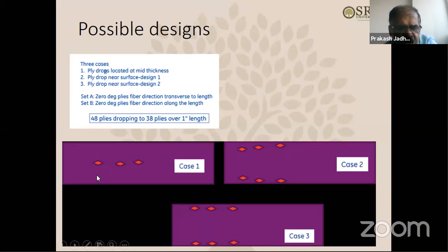So first we tried the coupons with ply drops located at the mid thickness. Okay. If you look at the ply drops at the mid thickness and then try to bend it, or maybe if you set up a cantilever test, okay, and try to bend it, these ply drops will be along the neutral axis. And of course, they will not have any effect on the structure, because they will be at the neutral axis if you bend them.